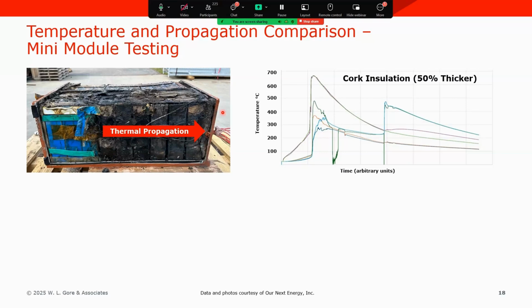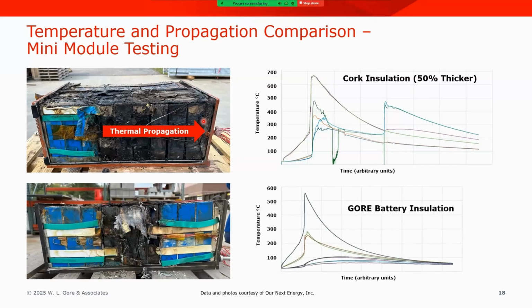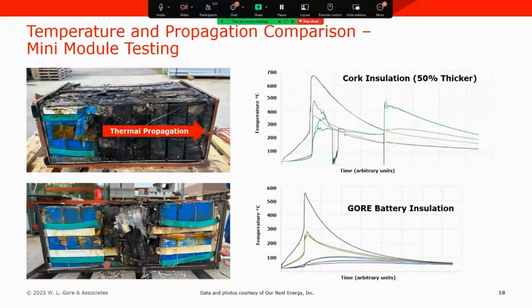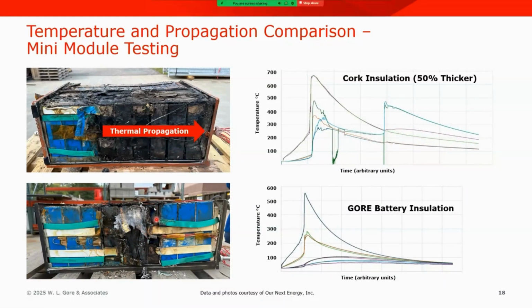Now let's compare it to the same exact test, same exact type of battery module, but now protected with GORE battery insulation. And you can see the results are pretty striking. Again, the center cell is the one placed into thermal runaway. It propagated just to the neighboring cells, but where the thermal barrier layer GORE battery insulation was deployed, we saw no additional propagation. So in essence, the GORE battery insulation was able to contain the thermal propagation just to the cells that were between the two layers.